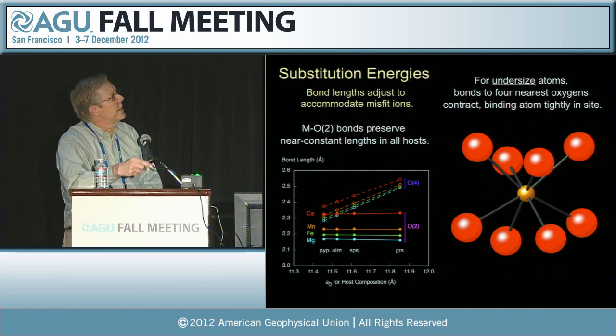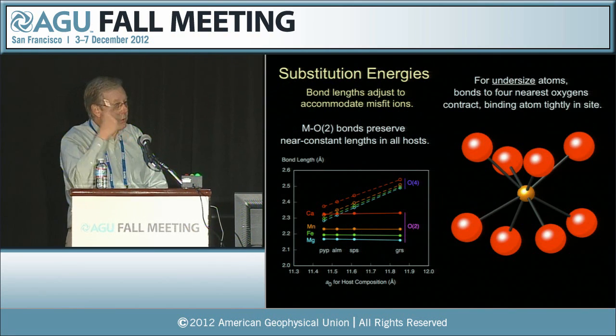And the reason for that has to do with the way in which the bond lengths adjust in order to accommodate these misfit ions. So plotted at the lower left are bond lengths for the relaxed configurations, and in each of these groups of 8 oxygens, 4 of them are closer in and 4 of them are further out. So these are the closer in, these are further out.